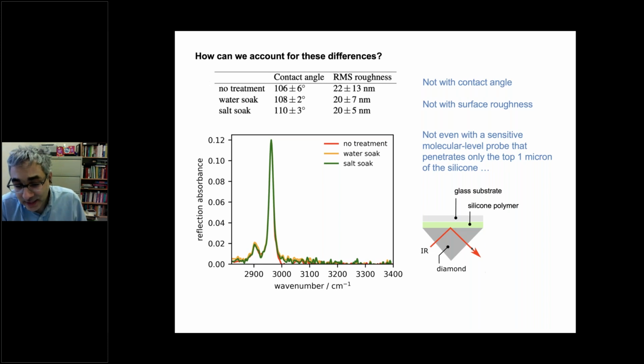Of the surface. And to do this, what we do is we bounce infrared light through a prism, and then it interacts with the silicones. We put the silicone upside down so it contacts the prism, and we collect the spectra. And these two peaks that you can see here on the left-hand side basically show you the symmetric and anti-symmetric stretching of the methyl group. This is a carbon-hydrogen functional group on the surface of the silicone, which is responsible for imparting hydrophobicity to the